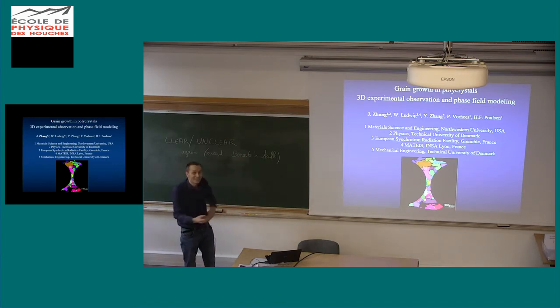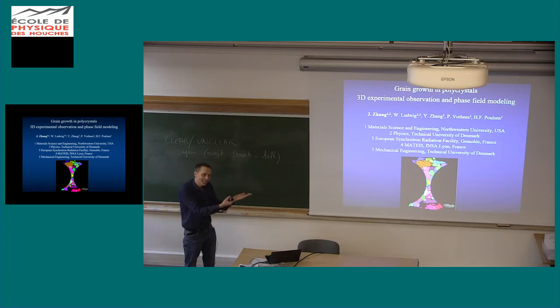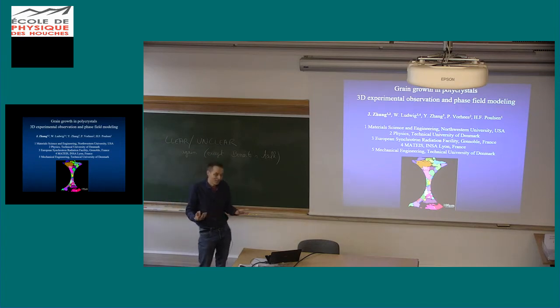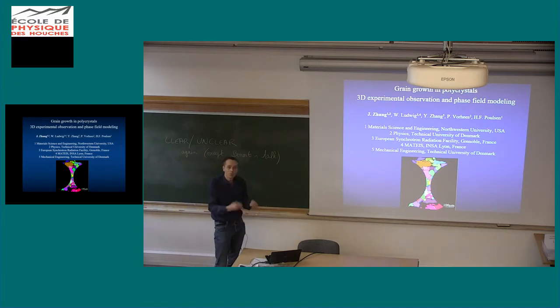And by the way, probably dynamic crystallization has happened as you have stamped a sheet of 1 mm thick aluminum to end up with something like 100 micrometer thickness. And while it's fully recrystallized, we can look at the grain shapes here, but there must have been recrystallization and growth during this process because it heats a lot and it deforms a lot. So this is a whole topic in itself. And by the way, it's also interesting to look into this grain structure because if there's strong diffraction events, as you use it as a lens, you have contrast in your images. It's not an ideal lens. So maybe there's something to be optimized in terms of microstructure of these lenses.